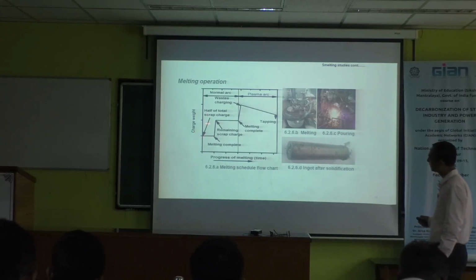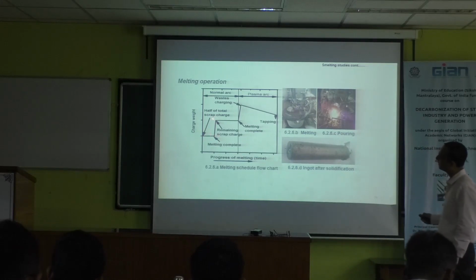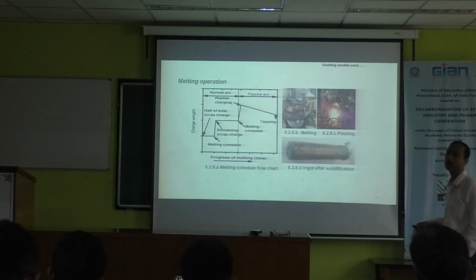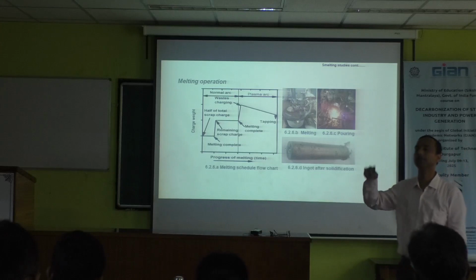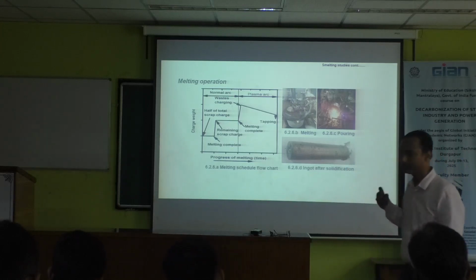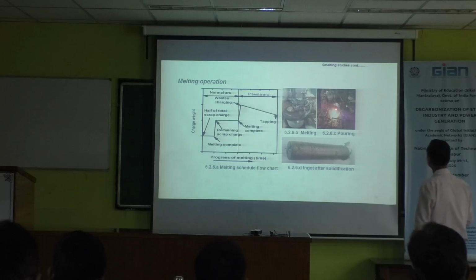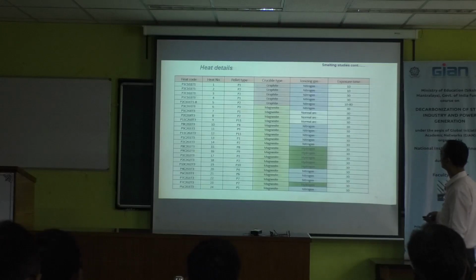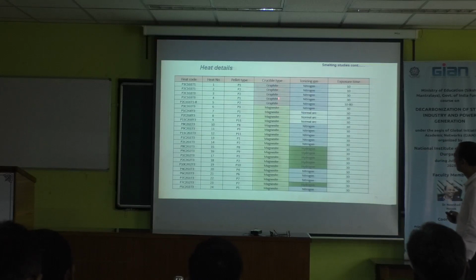Half of the scrap material we have melted first, then the remaining scrap material is melted. When the total metal pool is prepared, then you can see the switch over from normal arc to plasma, meaning we just introduce the gas so that the plasma will generate. Then after melting, gradually we are taking out the samples. These are the different materials, like in the case of different crucibles, I have discussed graphite crucible, magnesite crucible, different ionizing gas, different exposure time.